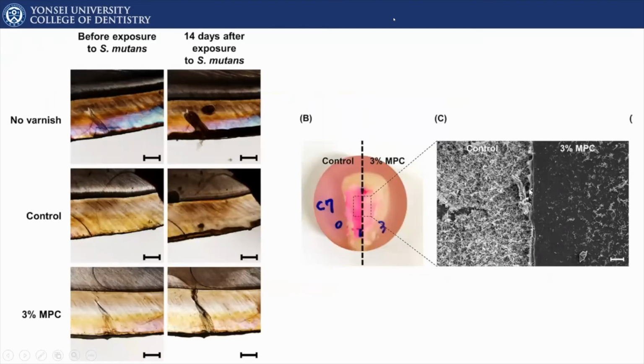So we wanted to see whether this will be effective in clinical situations. To mimic the clinical situation, we have this section of enamel and dentin, where we have one with no varnish, one with simple varnish without any MPC, and one with 3% varnish. As you can see here, the thick layer indicates the 14 days after exposure to Streptococcus mutans, resulting in decay of this layer. The fluoride varnish has some prevention, but there's still some of this black area of decay. Whereas incorporation of 3% MPC has a very good effect in terms of prevention. This can be dramatically shown in this picture on the right, where we have a division with control and 3% MPC, and this dramatically reduces the number of bacteria attached, as indicated by SEM images, as well as disclosing agent results, as you can see here.